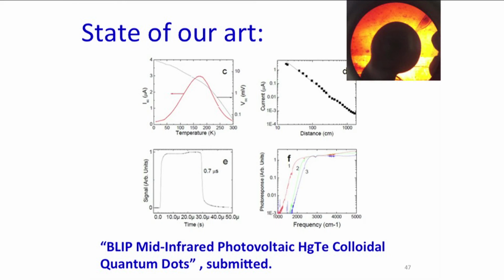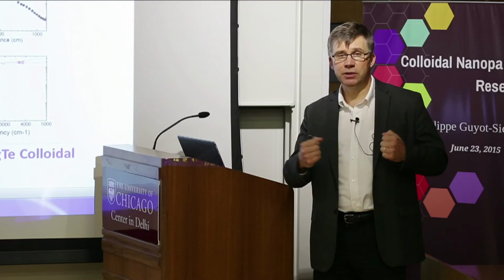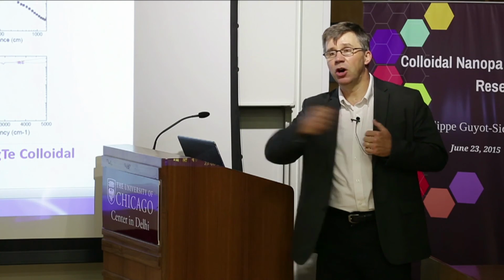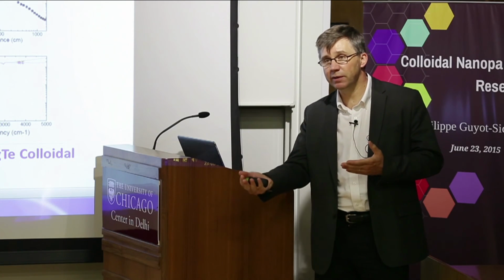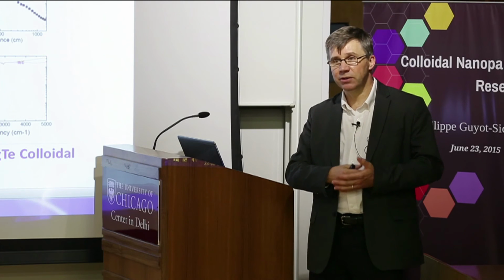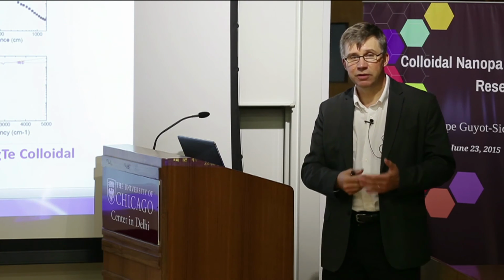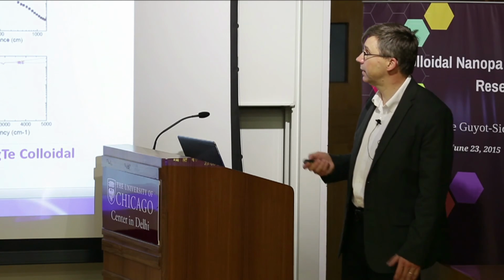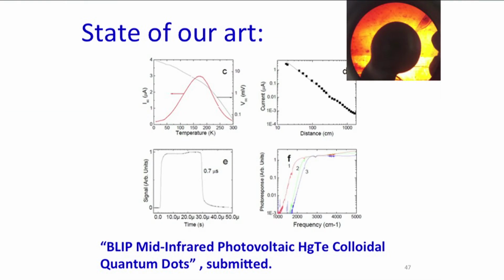And the reason for the decrease is that the charge carrier separation gets worse as you go to lower and lower temperature, because it takes longer and longer for the electron to hop. It's a thermally activated process. So as you go to lower temperature, the electron is kind of stuck inside the particle, so the efficiency of charge separation drops dramatically. At least that's how we understand this drop.